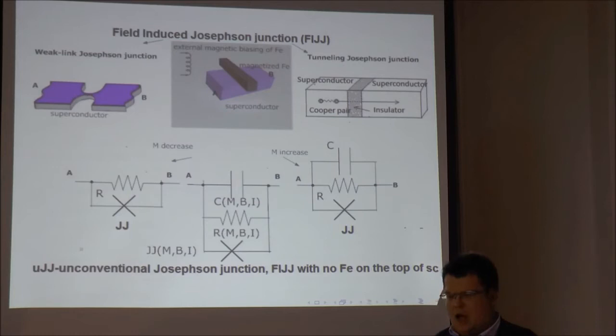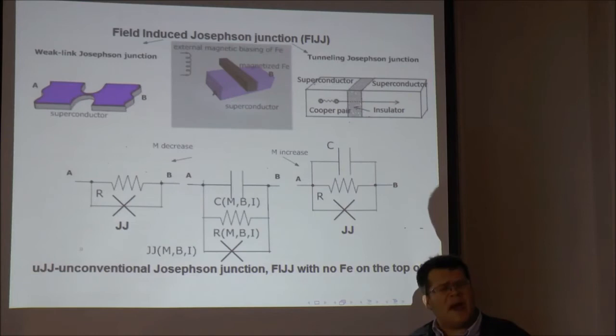This will, of course, also depend on the thickness of the superconductor, because basically we suppose not to go into smaller dimensions than one coherence length. To give you the number, in aluminium probably it is 3,000 angstrom, the size of the coherence length. So if you go below, then the pairing mechanism is no longer working effectively. So the state is no longer superconducting, or at least superconductivity is not so stable, let's say.